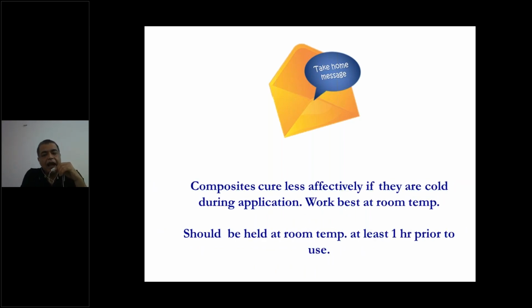Many of us have a habit of keeping our composite kits inside the refrigerator, especially in warm weather like this. And when the composites are cold, they actually cure less effectively. So it should be kept at room temperature at least 1 hour prior to use. Nowadays, we also recommend pre-warming of composite because that can increase the conversion of monomers into polymers.